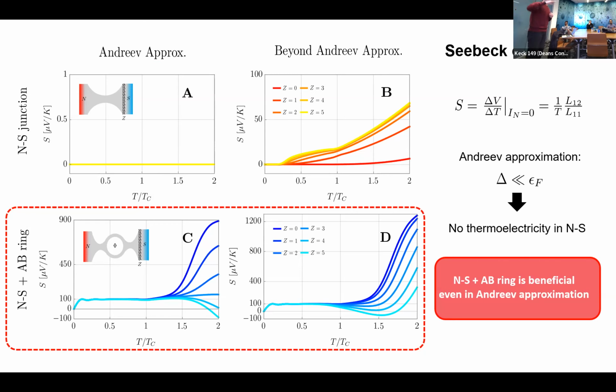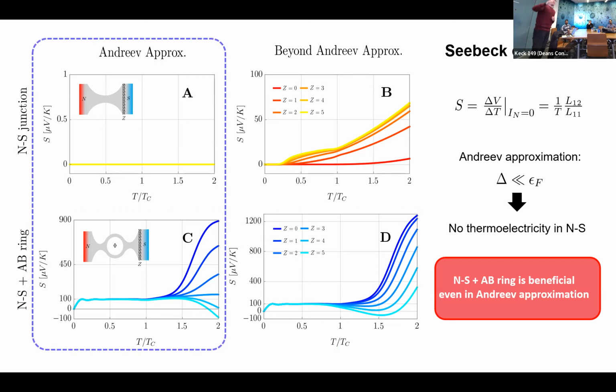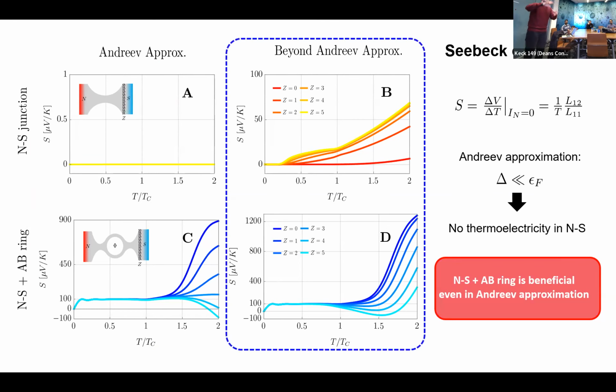Let me stress also that here, for both configurations, we consider two different regimes. A regime which is called the Andreev approximation, which happens when Delta, the energy gap of the superconductor, is much smaller than the Fermi energy. And we also consider the case in which we go beyond the Andreev approximation, so we relax this limit. It's very important to distinguish between these two different regimes, because usually in the literature there are a lot of papers that just talk about the Andreev approximation, but we will understand in a minute that this is not the best situation possible if one is interested in describing the thermoelectrical properties of a system.